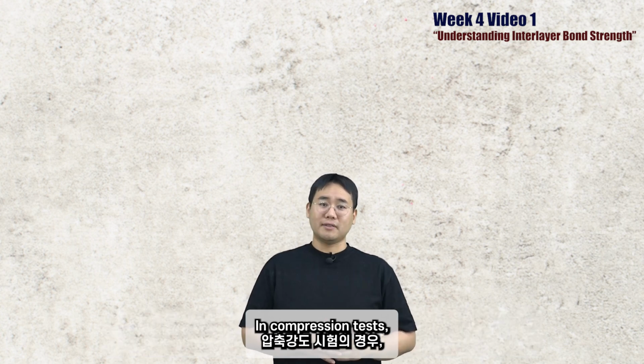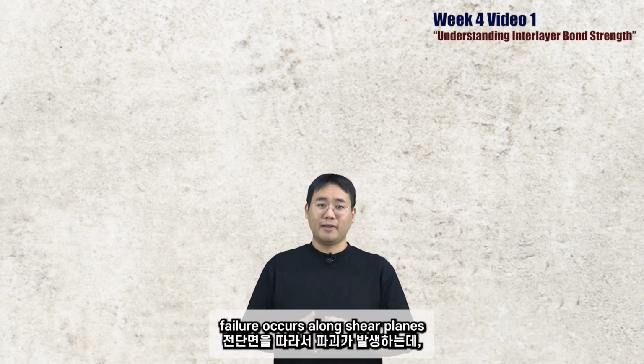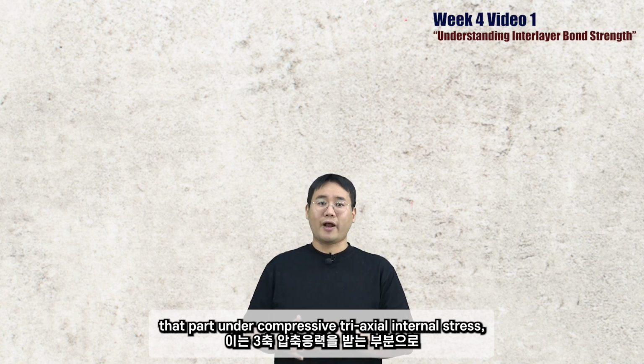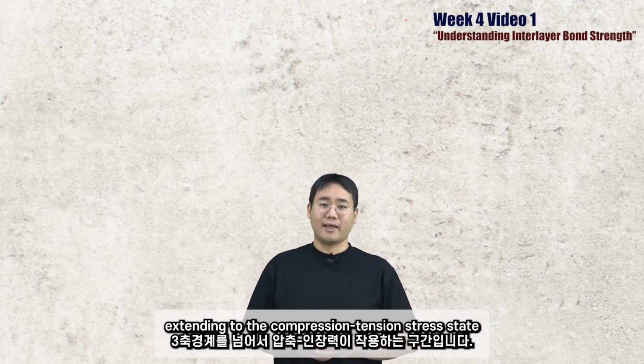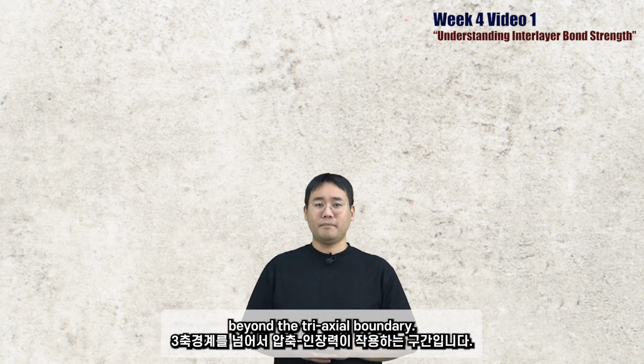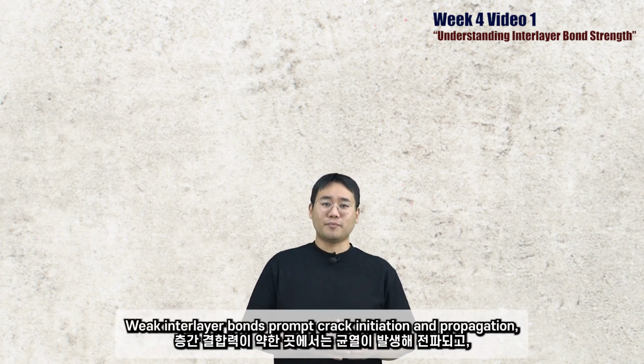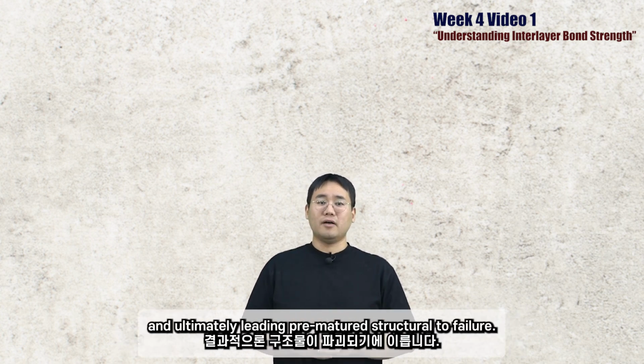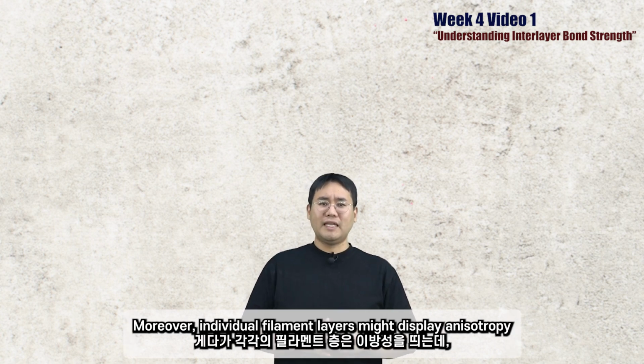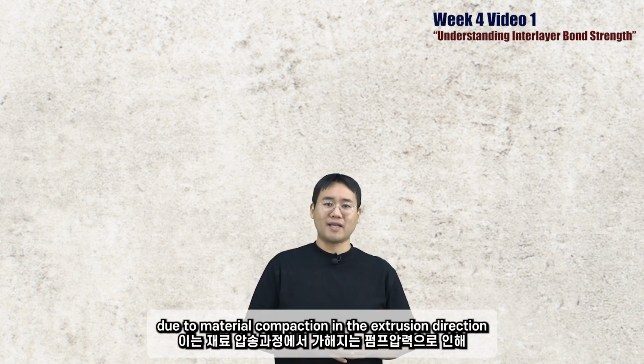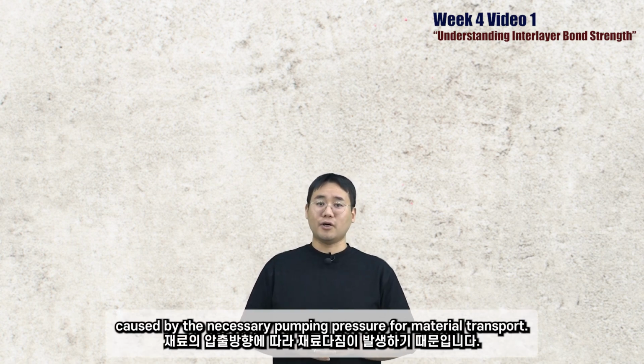In compression tests, failure occurs along the shear planes that form under compressive triaxial internal stress, extending to the compression-tension stress states beyond the triaxial boundary. Weak interlayer bonds prompt crack initiation and propagation, causing filament layers to detach and ultimately leading to premature structural failure. Moreover, individual filament layers might display anisotropy due to material compaction in the extrusion direction caused by the pumping pressure necessary for material transport.